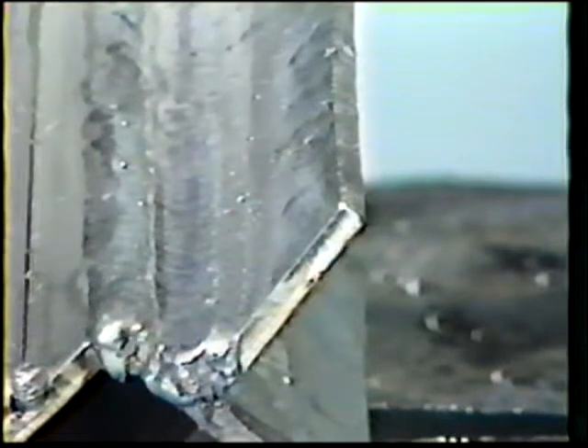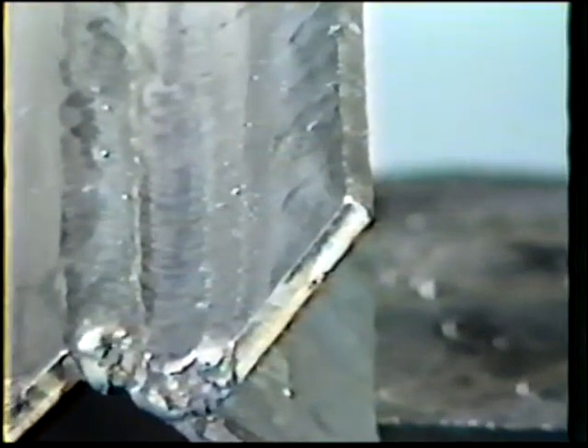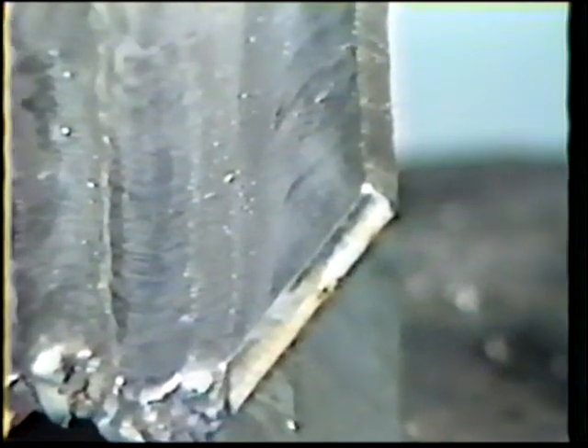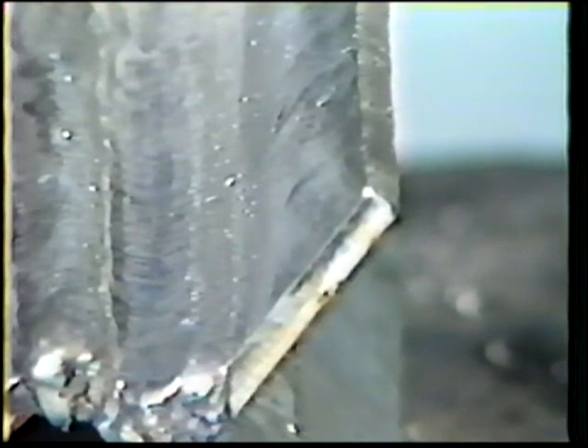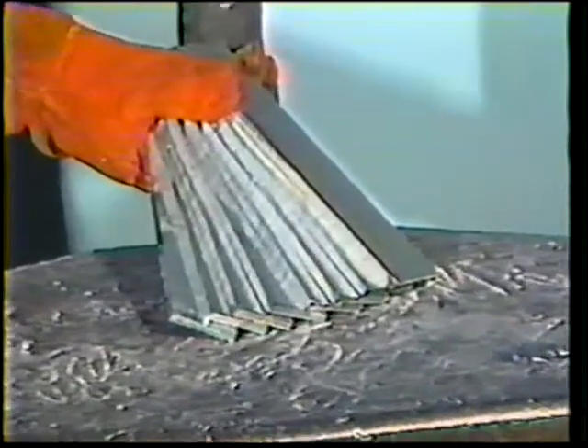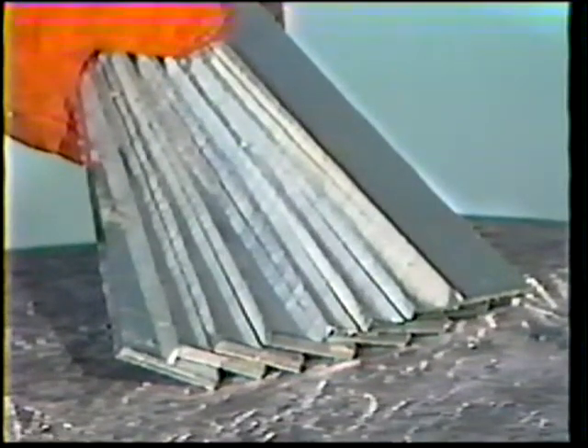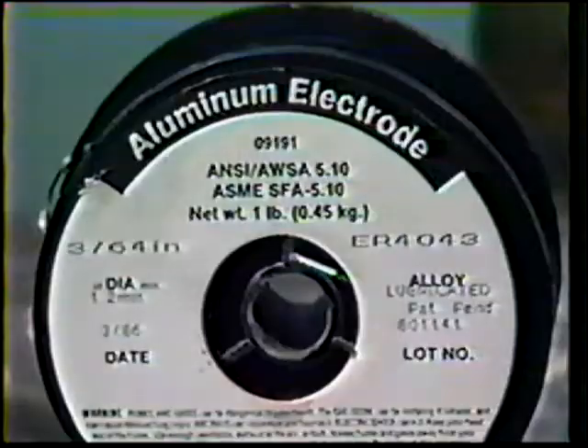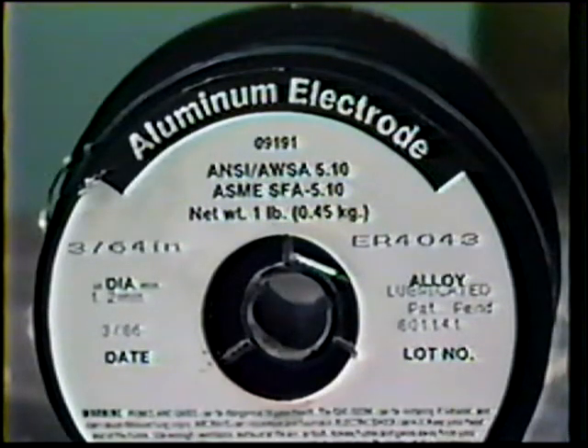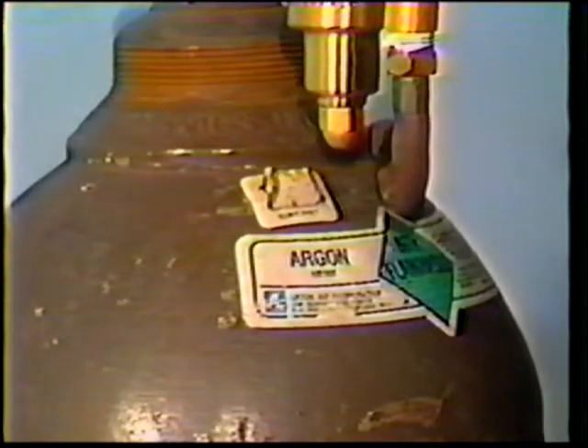The objective of this job practice is to develop skill to produce quality single and multiple pass fillet welds on 250 thousandths inch thick aluminum in the flat position. For this exercise, you will need 8 pieces of 250 thousandths inch aluminum plate to form each workpiece. The electrode wire is 3/64 inch diameter, ER4043. The shielding gas remains welding grade argon.